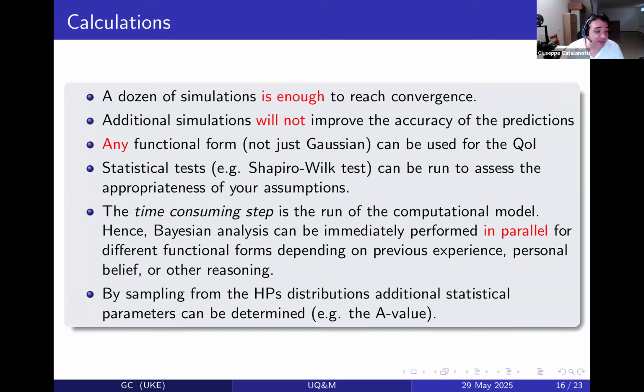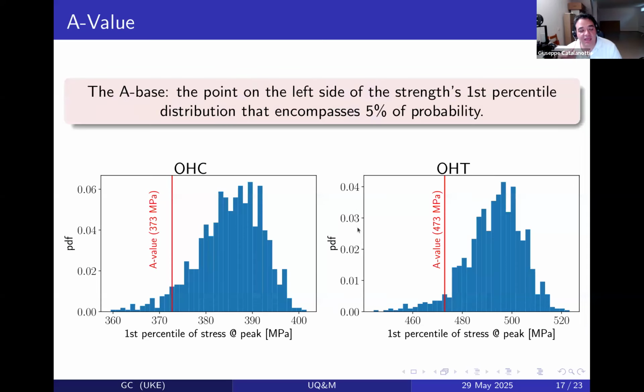So as I said, I repeat again, the time-consuming step is running the computational model. Bayesian analysis can be immediately performed in parallel, and you can do this for different functional forms. And by sampling from the distribution, you can get any statistical parameter, the entire distribution, a certain quantile, or, for example, what is very well renowned in the aeronautic industry, the A value. And what is the A value? I'm making an example here. The A basis value is the point on the left side of the strength distribution that encompasses 5% of probability.